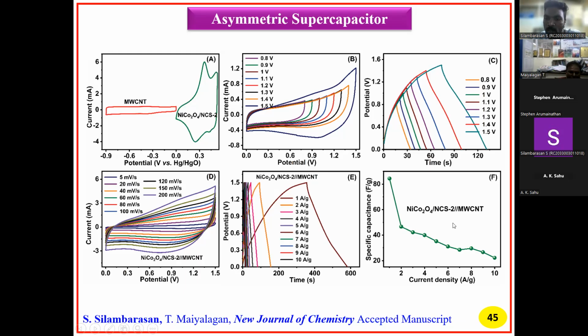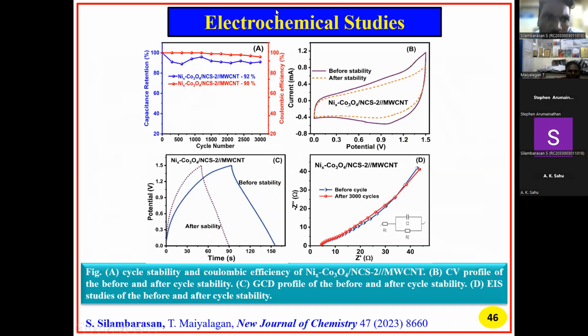So next, figure F is the specific capacitance versus current density. Overall, at around 1 ampere in the two-electrode system, the specific capacitance is 85. Next one, figure A shows the capacitance retention in the two-electrode system at 92%, with a Coulombic efficiency of 98%, measured over 3000 cycles.